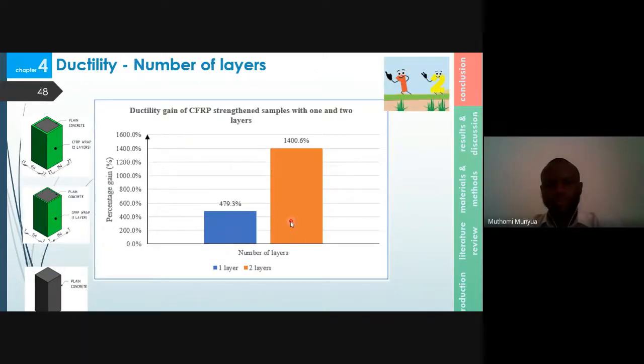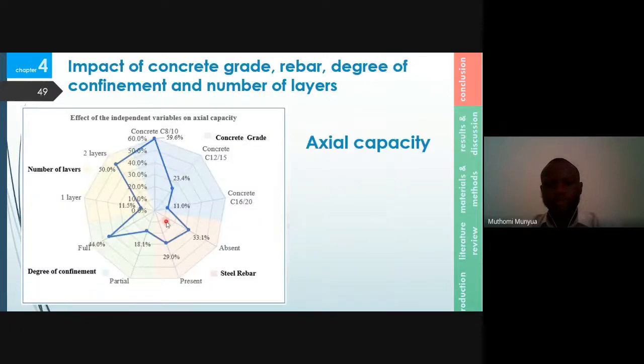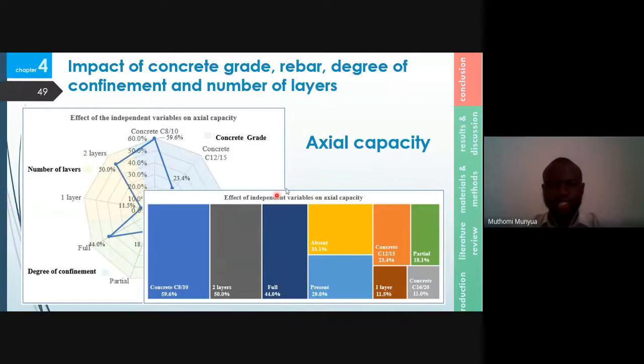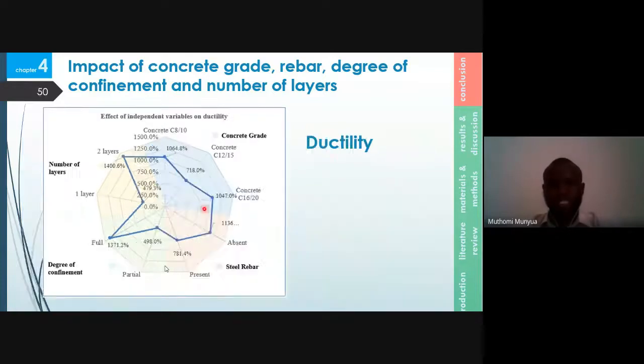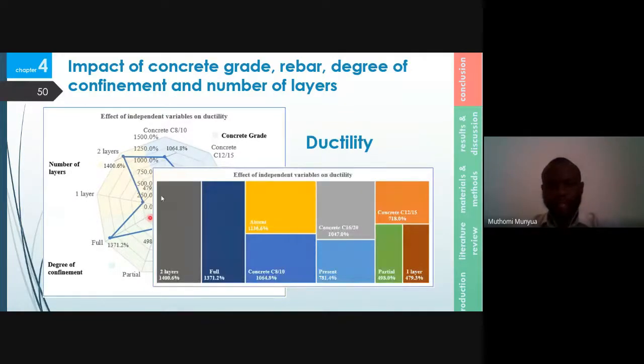To find out the impact of the variables, it was represented in a radar chart. A radar chart is a graphical technique of visualizing multivariable data. In this case, we found concrete C8/10 had the highest effect, and the number of layers closely followed. This is clearly illustrated by use of a tree map. Same procedure for ductility: two layers had the highest effect, and using one layer had the least effect.